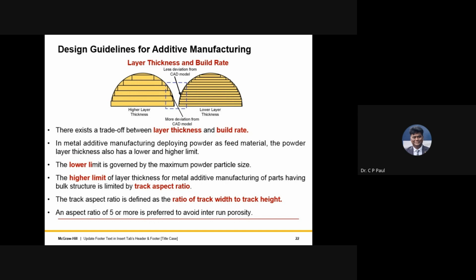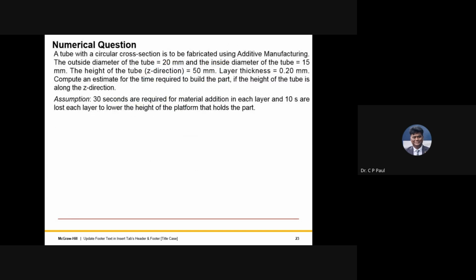In general, the lower limit of the layer thickness is governed by the maximum powder particle size that we are using, maybe powder bed fusion or direct energy deposition in any of these things. At the same time, the higher limit of the layer thickness is defined by the track aspect ratio. You must be knowing in most of the cases, the track aspect ratio, meaning the width of the track divided by the height of the track while depositing the material, has to be more than 5. Otherwise, it will lead to interrun porosity. So this is the way how the layer thickness is defined and build rate is taken care of.